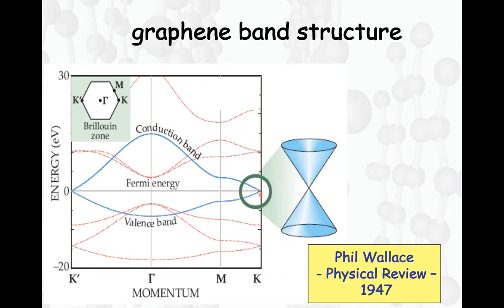And so this means all of the low energy states have practically the same momentum. And that means that their ability to resolve space is limited, by the uncertainty principle, by one over the range of momenta that is available at low energy. And that doesn't allow them to see whether a system is actually commensurate or incommensurate at the atomic level. Only the longer distance Moiré periodicity is seen.